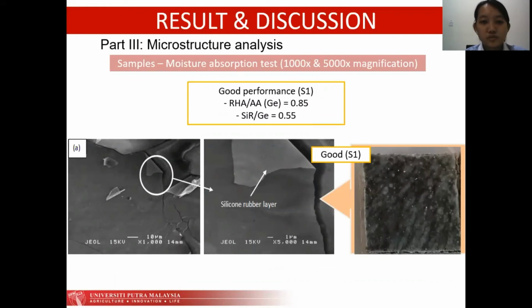So this is the sample for the moisture absorption test with good performance. From the figure, it reveals that the silicone rubber formed the outer layer of the sample without any crack formation, and a highly viscous geopolymer composite matrix forms this layer with an RHA and AA ratio of 0.85. Since the content of RHA is higher, only a small amount of silicone rubber can be blended with the geopolymer composite matrix, and so the unreacted silicone rubber forms a thin layer beneath the geopolymer composite matrix. The silicone rubber is hydrophobic, so it acts as a barrier against moisture.